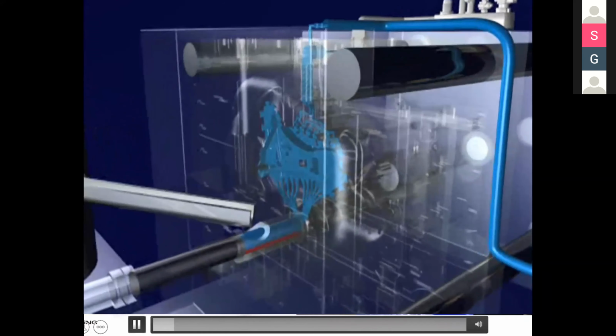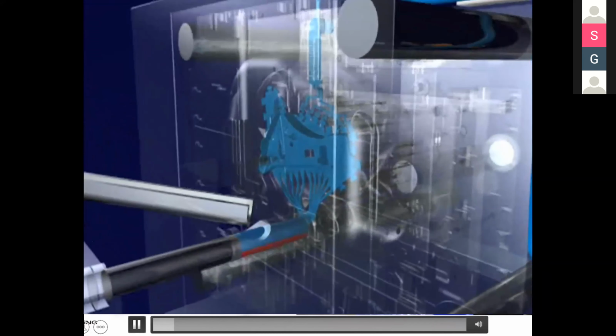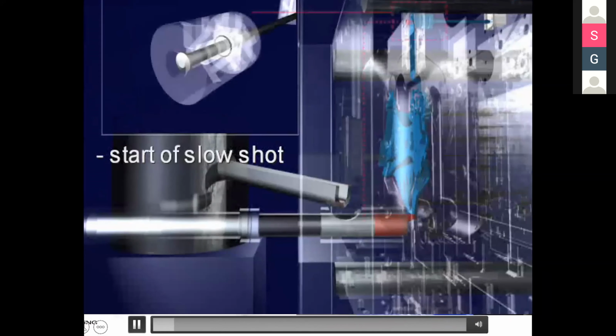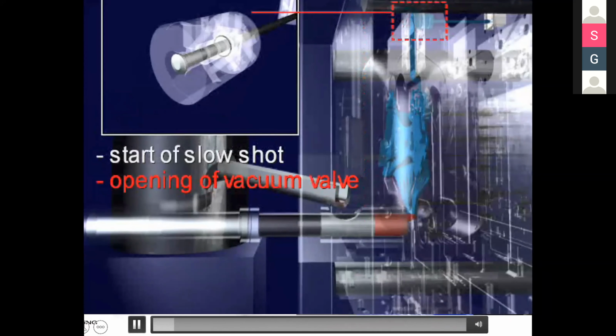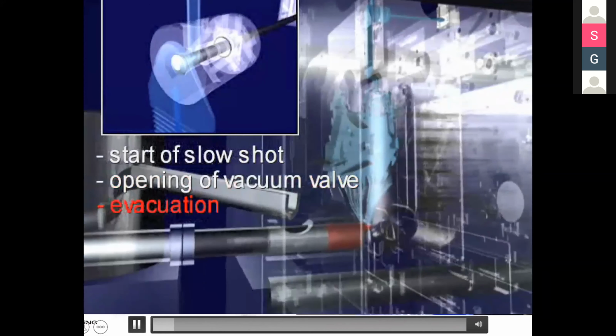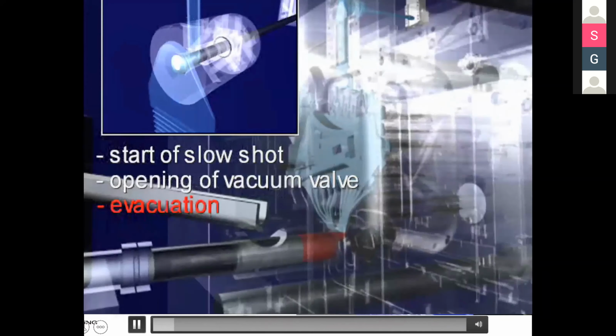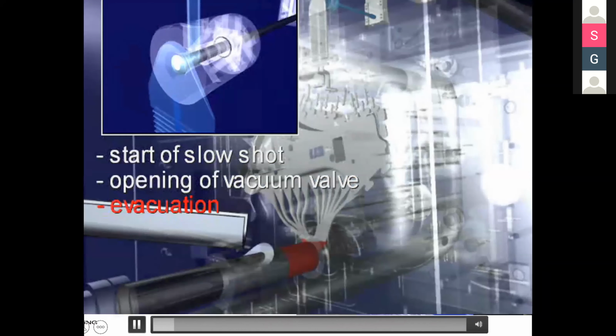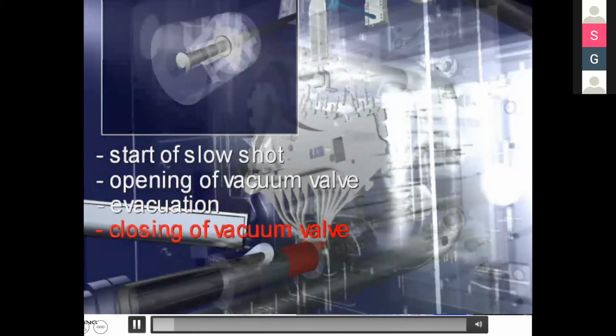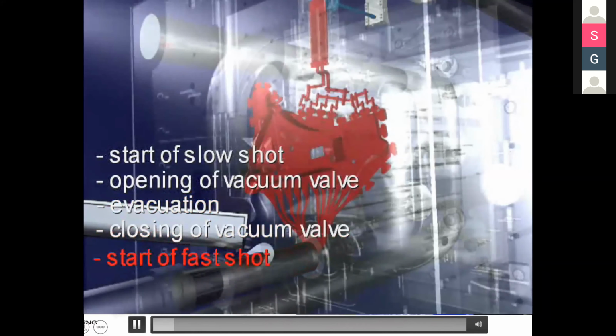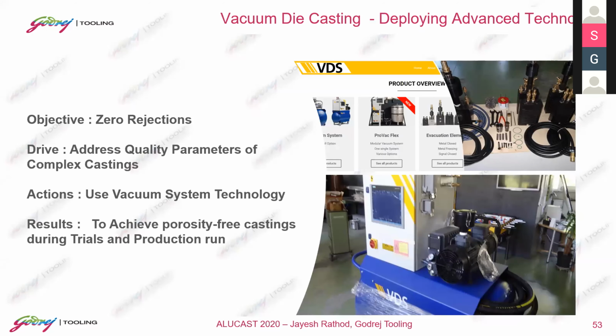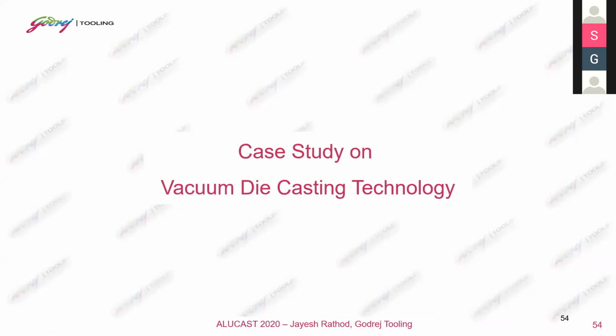In the first phase, that is metal pouring, it starts off with the slow shot. When the shot sleeve is completely sealed, the vacuum valve will get opened and suck away all the air which is inside the cavity. That evacuation is happening at the other end through the chill vent in this case. Then the vacuum valve closes, and the second and third phase start, which is the faster phase. So this is the way vacuum technology works.